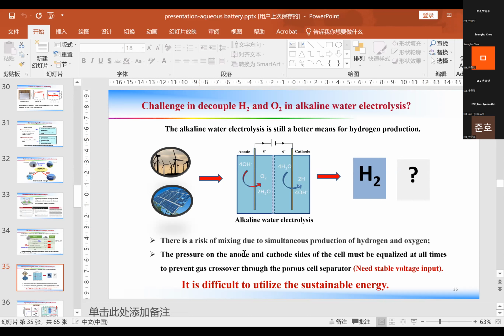But the problem is there is a risk of mixing during simultaneous production of hydrogen and oxygen. Oxygen and hydrogen will steadily evolve this way, and then the pressure on both the anode and the cathode side, the cell must be equalized at all times to prevent gas crossover through the porous cell separators. So we must have a stable voltage input, and it is very difficult to utilize the sustainable energy. So this is the conventional alkaline electrolysis.